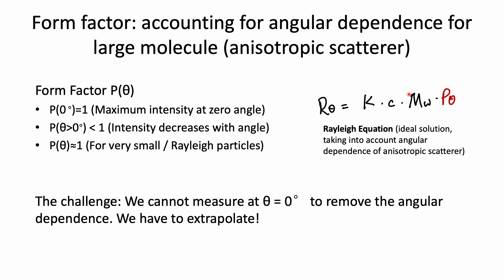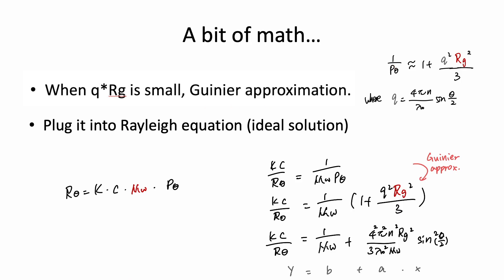To analyze molecular weight using the Rayleigh equation, the simplest thing is to measure the scattered light intensity at θ = 0. However, in that forward direction, the detector is overwhelmed by the intensity of the incident laser light, so it is difficult to measure directly at θ = 0 and we have to extrapolate. It turns out the form factor can be approximated by the Guinier approximation: 1/P(θ) ≈ 1 + q²Rg²/3, where Rg is the radius of gyration and q is the scattering vector: q = (4πn/λ) × sin(θ/2).